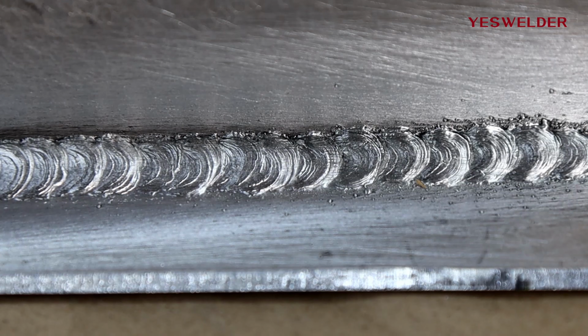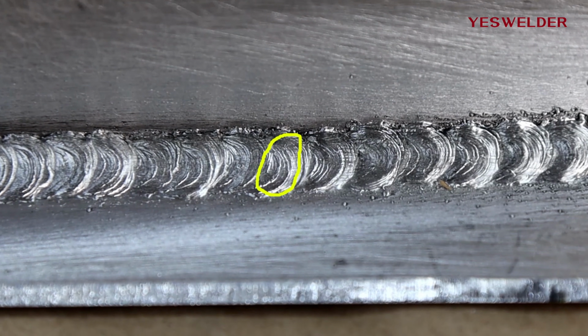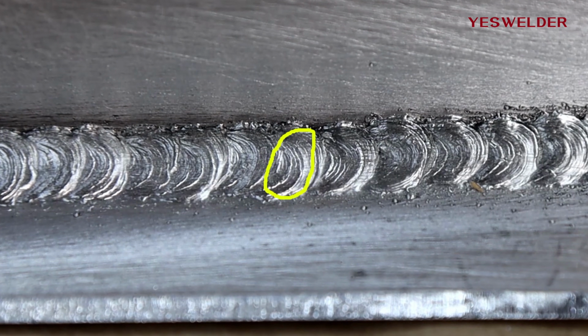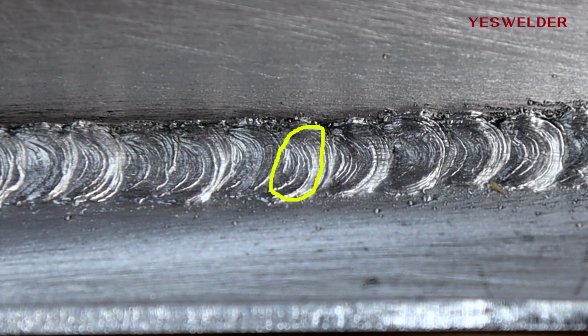When this electrical circuit is open and closed many times a second, that causes the popping and spattering you may be familiar with if you've ever MIG welded before, and it can be worse when you're MIG welding aluminum. Here's a piece of aluminum that I welded using short circuit MIG welding. You can see all of these tiny ripples that are in the weld. This is caused by that electrical circuit being closed and open many times per second. There also is just a little bit of spatter, but this weld really doesn't look all that bad.